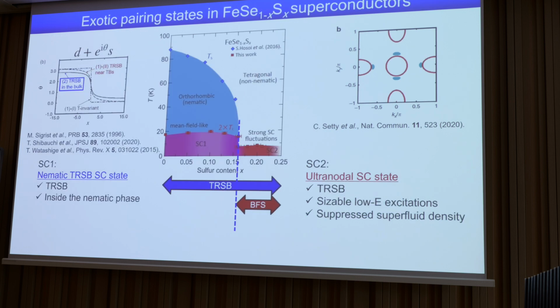So far, what we have observed is that time reversal symmetry breaking occurs throughout this phase diagram, both in SC1 and SC2. But only in the SC2 region do we have evidence for Bogoliubov surfaces. Why SC1 can also break time reversal symmetry is that in SC1 we are inside the nematic phase, so the crystal already has a domain structure, nematic domains.